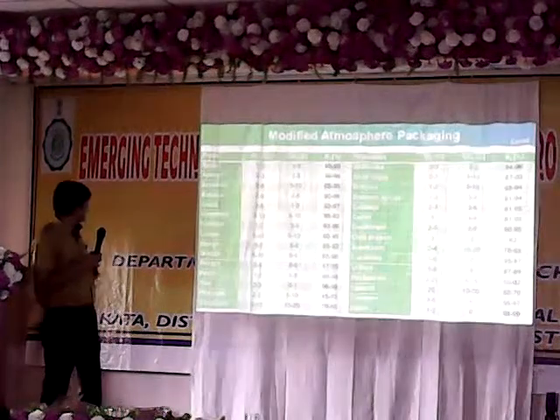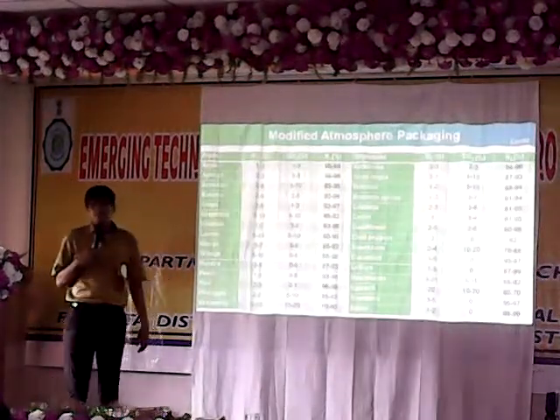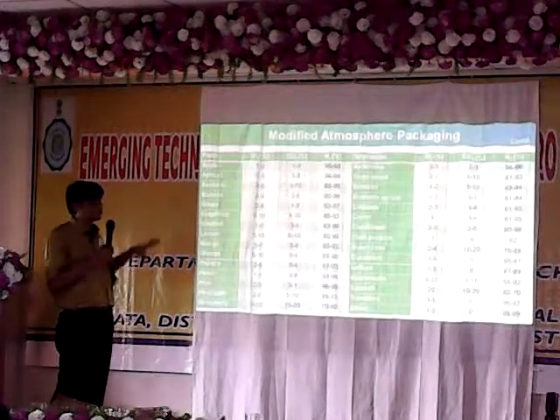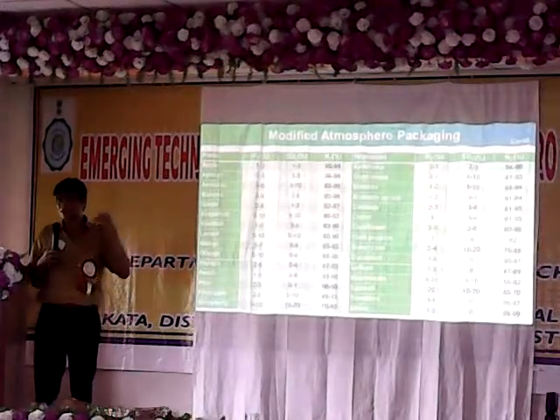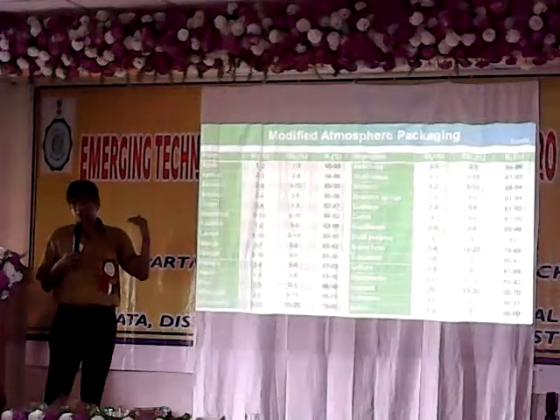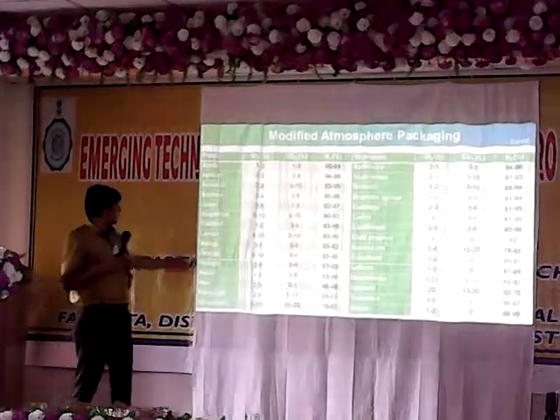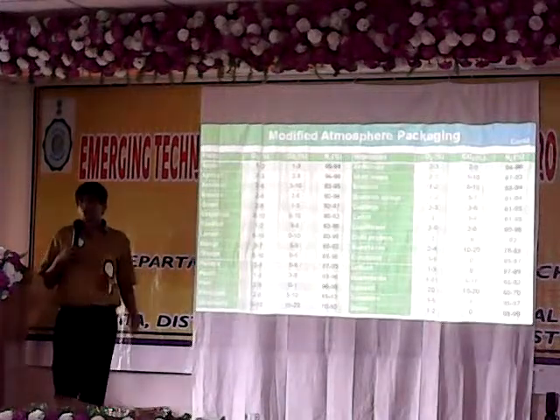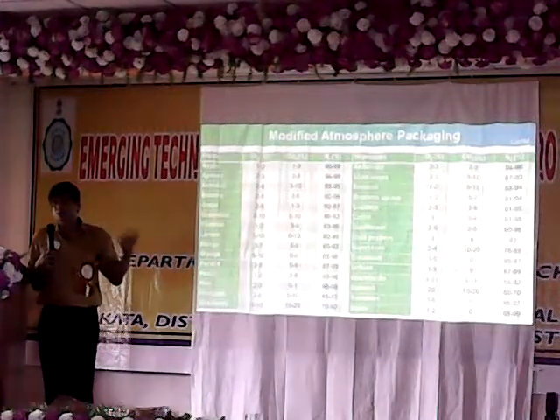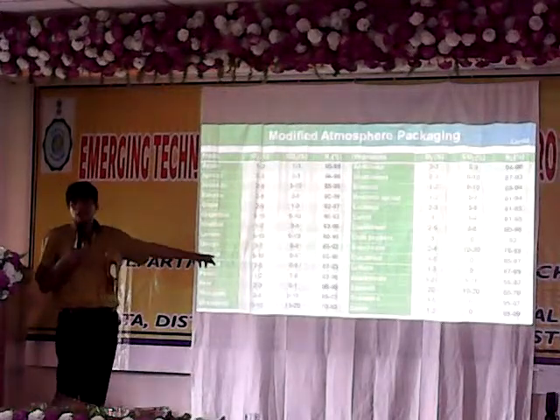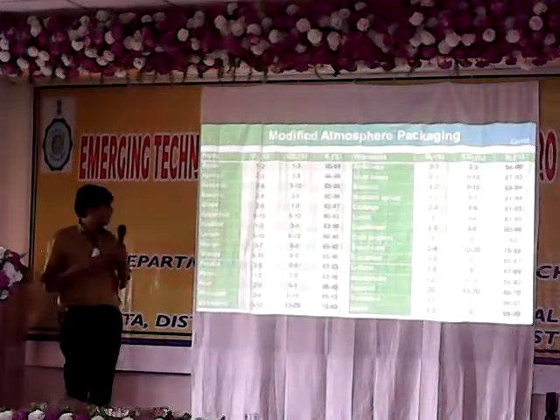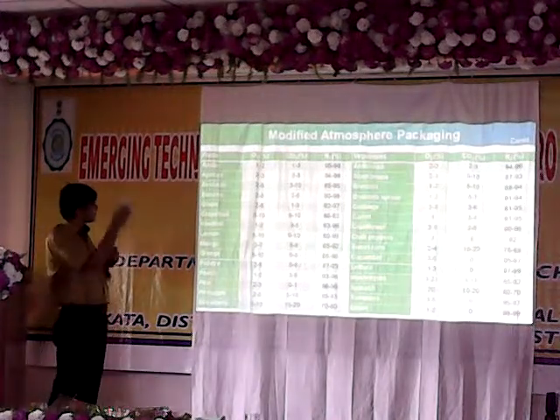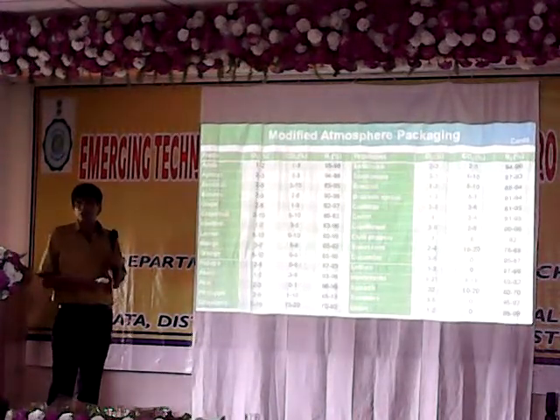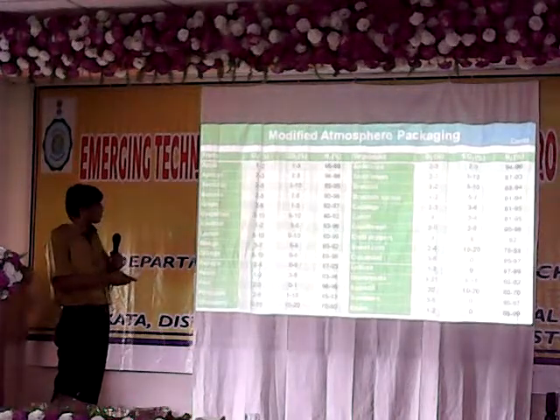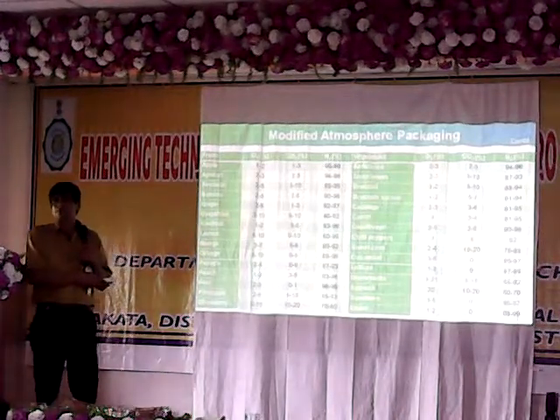Now these are the requirements of different commodities to be stabilized at different concentrations of oxygen, carbon dioxide and nitrogen. Mango, for example, is better served by 3% oxygen, which is almost one-seventh of the normal atmospheric 21%, and carbon dioxide of 5 to 8%. Carbon dioxide is 0.03% in the air, so this is almost 200 times higher. Likewise, we have different commodities, and depending upon the type of commodity, we need to select a kind of film so that we can establish a good equilibrium for the product to be stabilized.